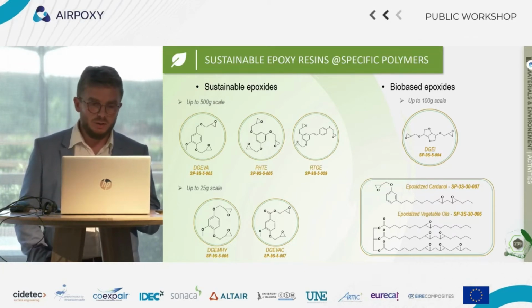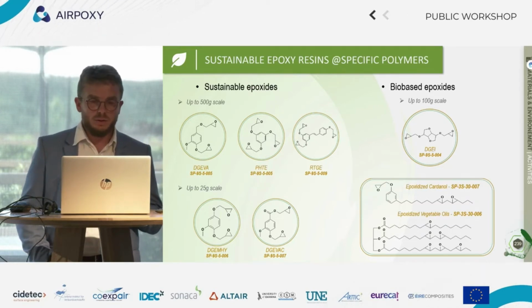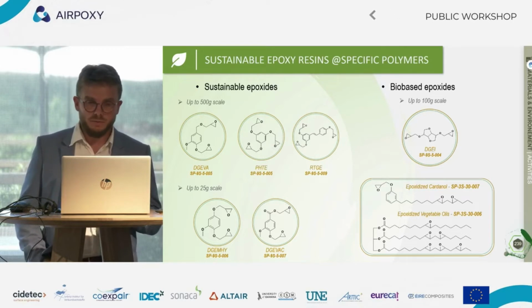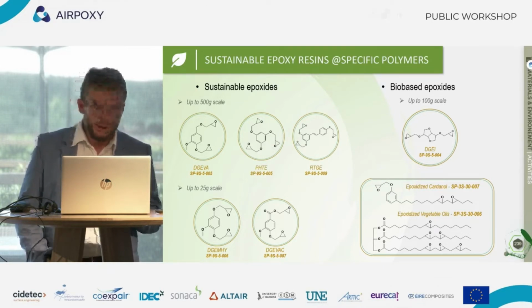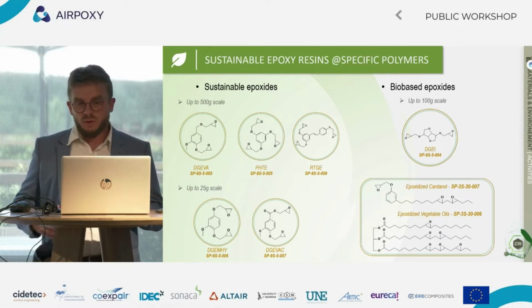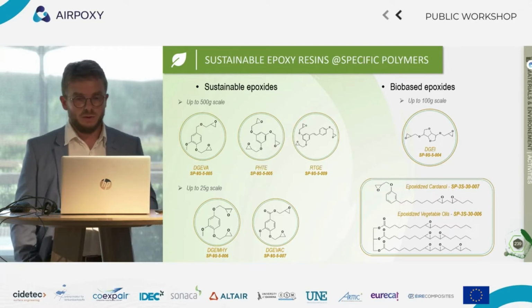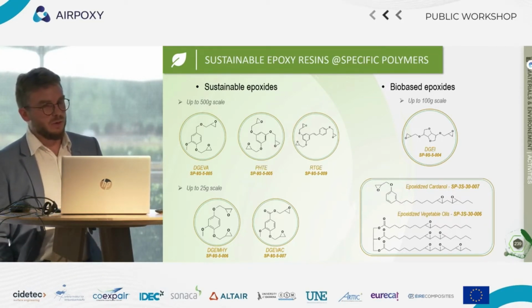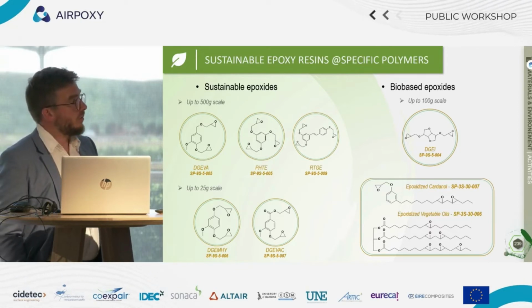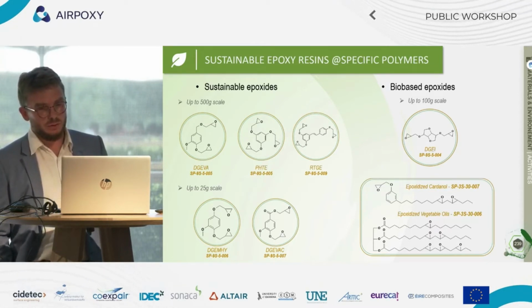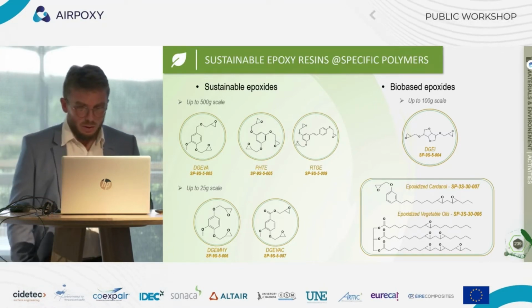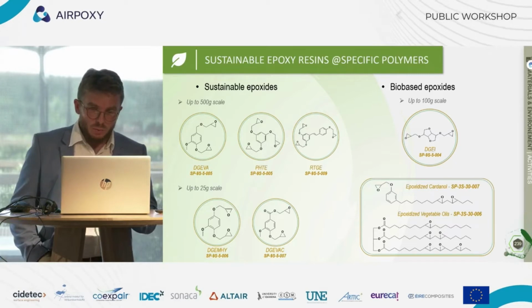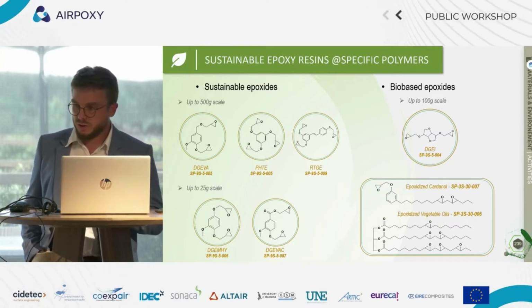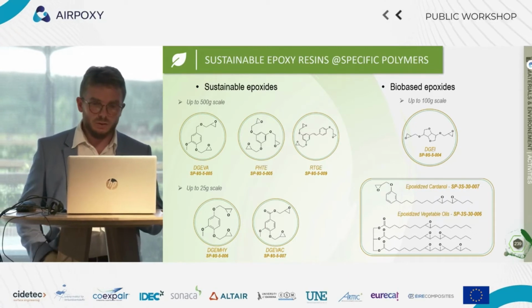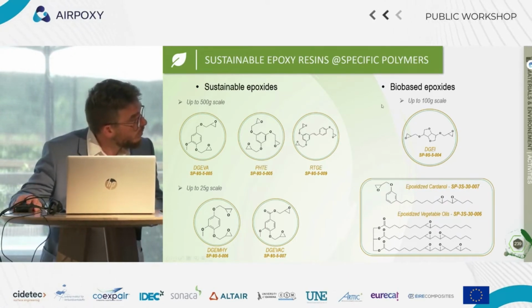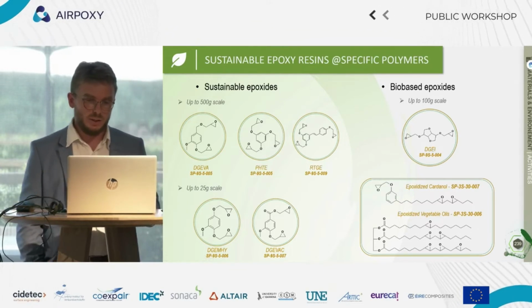So it's based on vanillin alcohol, phloroglucinol, resveratrol. So these are all aromatic phenols that can be extracted, for instance, from wine residue or from algae. And we convert them into epoxy, and we work on the chemical synthesis in order to have something relevant for pilot scale. And then we have some bio-based epoxies from isosorbide, for instance, which is this cycloaliphatic compound on the right-hand side. We also work on a derivative from cardanol, which can be extracted from cashew nuts. It's on the right-hand side, the one with the aliphatic chain and the aromatic ring.